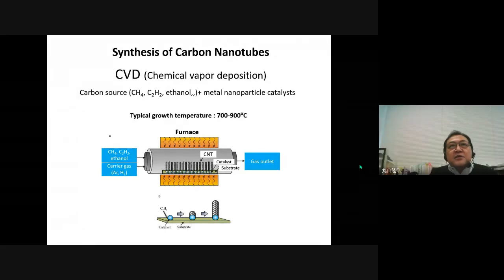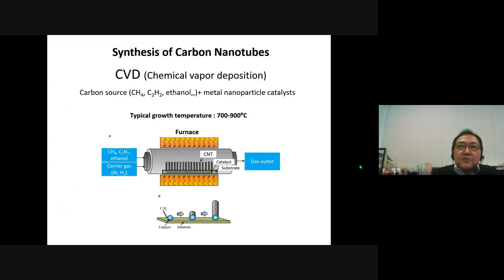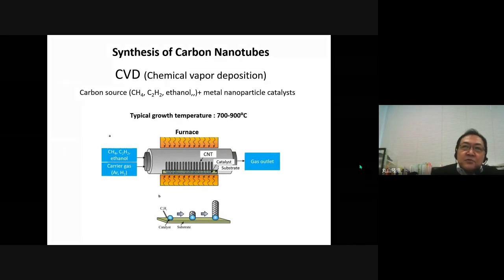At present, CVD, chemical vapor deposition, is widely used for carbon nanotube growth because CVD is suitable for mass production and cost-effective. In CVD, nano-sized metal particles are used to grow carbon nanotubes. They react with feedstock gas, such as hydrocarbon or alcohol gas, and decompose them to nucleate carbon nanotubes. In general, single-wall carbon nanotubes are grown at around 700 to 900 degrees C by CVD.